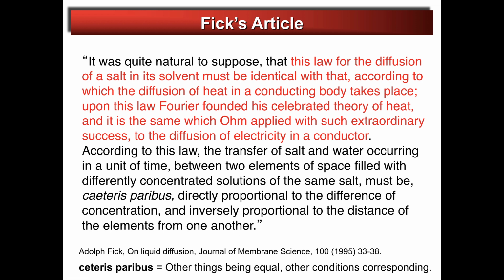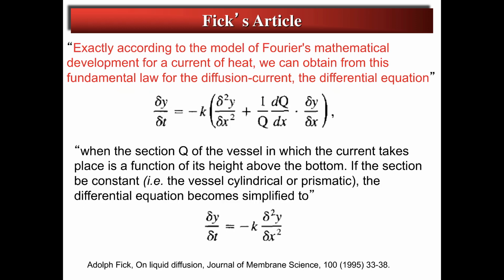That is, the flux of salt and water moving through a mixture where the salt concentration is different in one place than in another had to be proportional to the difference in concentration of salt between these two locations and inversely proportional to the distance between them.